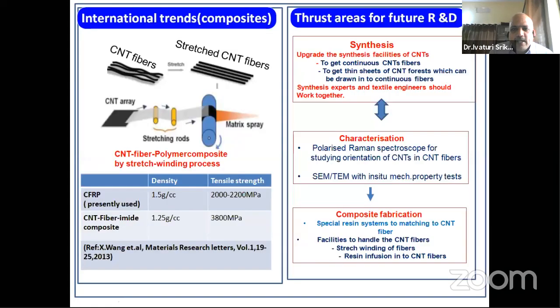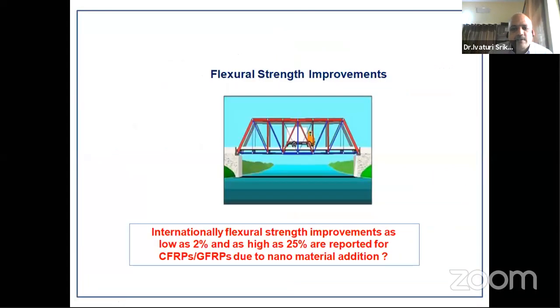So as a summary, what I can say is, there is a possibility of improving tensile strength of composites by 9% to less than 10%. That is also not because CNT takes the load, but because CNT improves the interface strength of a conventional composite. But there is scope to improve the tensile strength if you use continuous CNT fibers. That is still not evolved in India. Even globally, people have not used it for any application, but it is proven at the laboratory level.